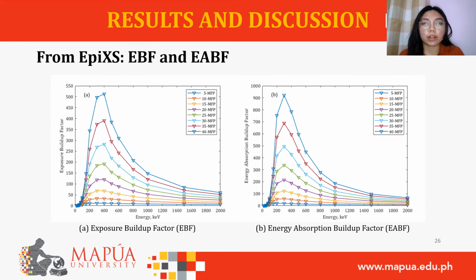The exposure buildup factor of sample CF05B00 at different values of mean free path was obtained. Based on graph A, it can be observed that at all MFPs, the values of EBF at low energies are low, subsequently peaked at about 400 kiloelectron volts, and then went down as the energy increased. These three phenomena can be attributed to the photon interaction dominant at each energy range, namely photoelectric absorption at low energies, Compton scattering at intermediate energies, and pair production at high energies.